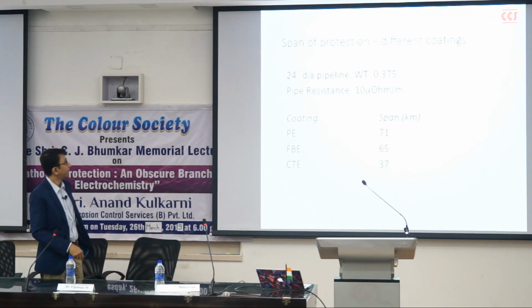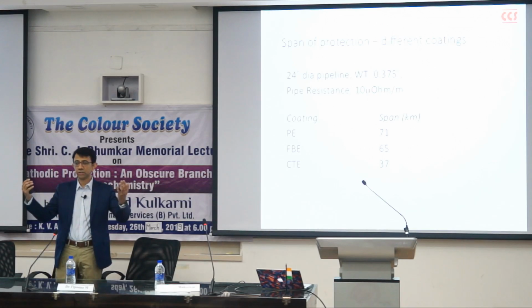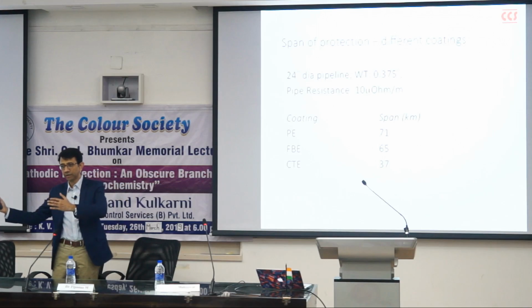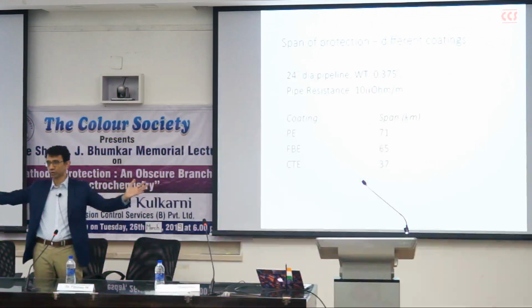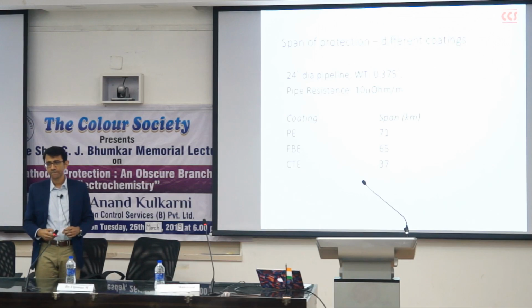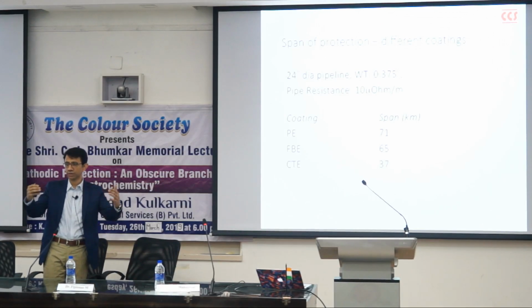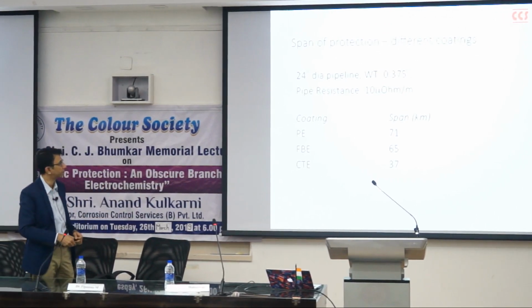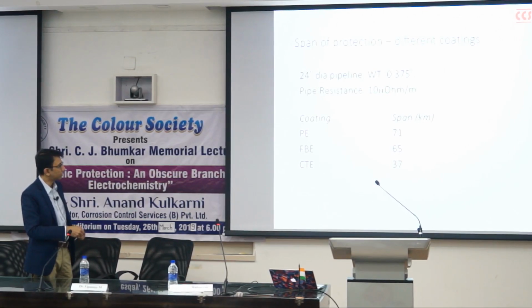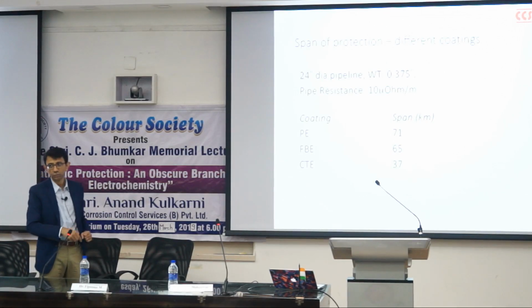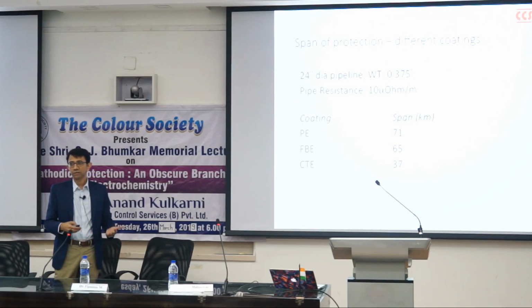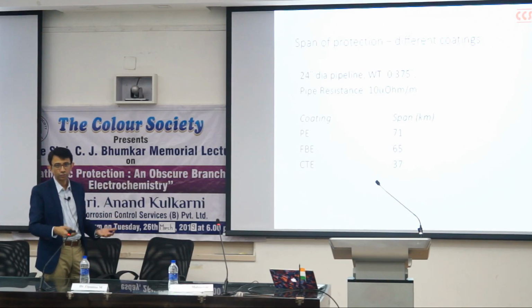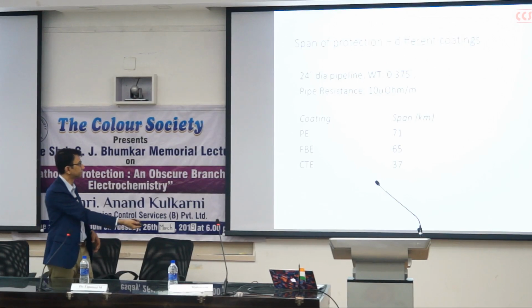This talks about span of protection for different coatings. So just imagine one CP station comprising one transformer rectifier, one anode bed, and the structure. And the structure is a long pipeline. So we have multiple such cathodic protection stations along the pipeline. So if you have a coal tar enamel coated pipe, you could protect 37 kilometers, with a fusion bonded epoxy 65 kilometers, with a polyethylene 71 kilometers. So you can see that better coatings obviously reduce the CP current demand.